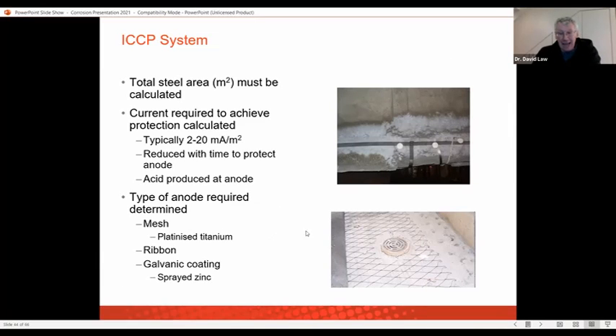So platinized titanium here, and I said you can also use a sort of galvanic coating or a conductive carbon coating, even as a paint, to be able to apply it. The mesh, usually you can apply the most current. So if you've got a lot of steel, it'd be mesh. Then you may go down to ribbon, and ribbon obviously can be slotted into quite small areas as well. And then if you don't need too much current, then the conductive paints can work quite well.